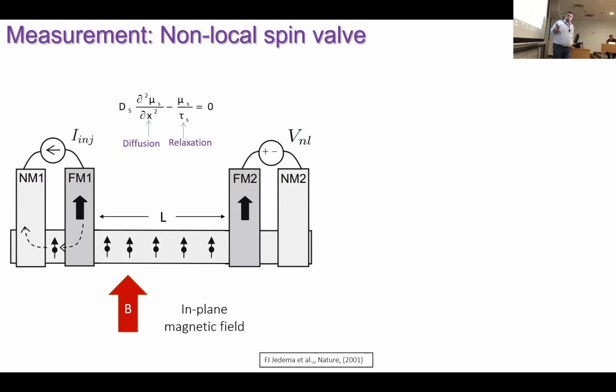So this is something we call the non-local spin valve geometry. Here, you are sending the charge current here. The charge current is only propagating in this area, but you are already creating a spin imbalance here. These are ferromagnetic contacts, so whenever you inject the charge current, it also becomes spin polarized, right? And the spins are not only diffusing here, they are also diffusing here. In this area, you don't have any net charge current propagation. Therefore, all you will be measuring at the other side of the device is any signal coming from the pure spin current rather than any charge contribution.